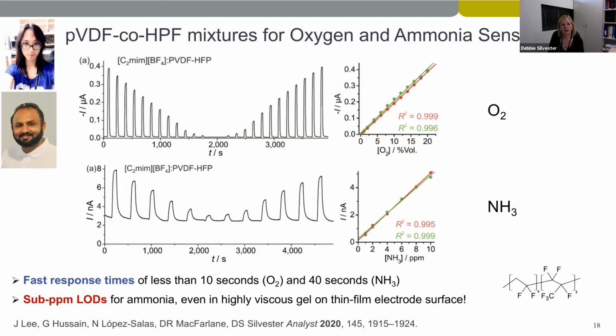And so Ginny carried out the oxygen experiments, and my former PhD student Ghulam carried out the ammonia experiments. This is a long-term chronoamperometric transient where we bias the potential where the gas oxidizes or reduces, and then we introduce the gas at different concentrations with a nitrogen flushing step in between just to observe the return to the baseline. You can see really nice responses to both oxygen and ammonia, and we get linear calibration graphs which overlay quite well for the descending and the ascending phases.